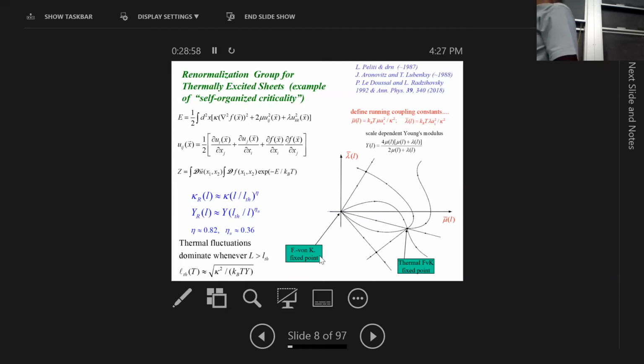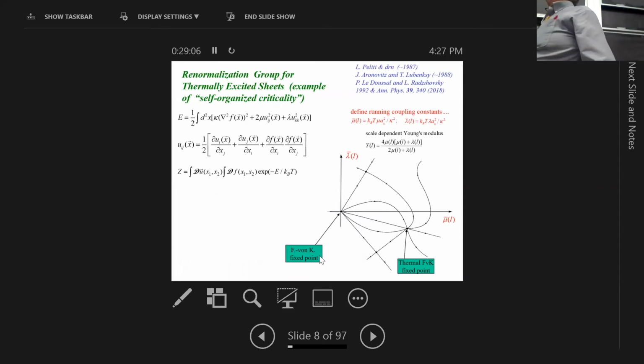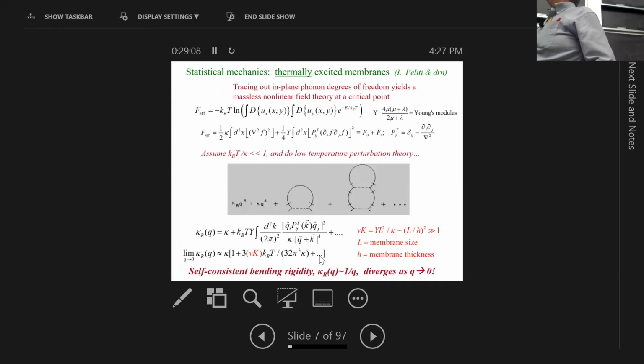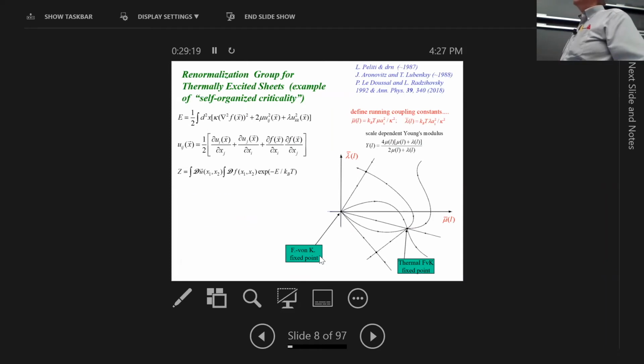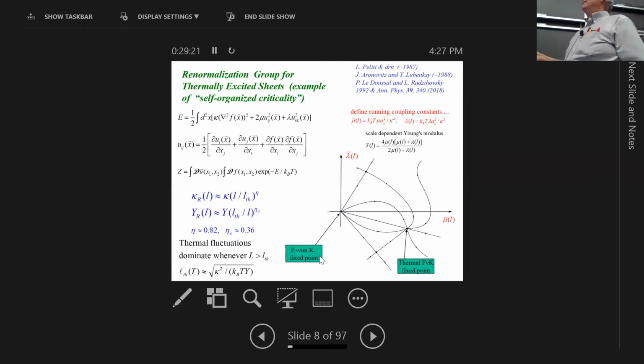Here's its exponent. And the crucial thing that tells you is a kind of Ginzburg criterion that tells you when this is going to be important. The easiest way to get it is to go back here and ask, when is this correction going to be comparable to what it's correcting? And that gives you a length scale beyond which you better pay attention to these scale-dependent elastic constants. And here's its functional form, depends on temperature. So at zero temperature, you don't have to worry about this stuff. You might have to worry about quantum fluctuations, but you don't have to worry about these thermal undulations.